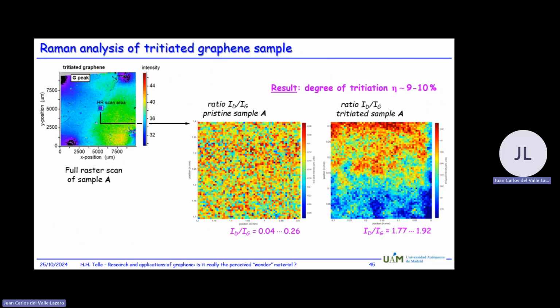Again, Raman spectroscopy will not give you a tremendous accuracy of how many particles were absorbed, because it's very difficult to calibrate this. It's much easier if you use your graphene with something absorbed as a sensor, meaning you have attached a voltage across and you measure the current. And with that, it was demonstrated that you can go to single particle.